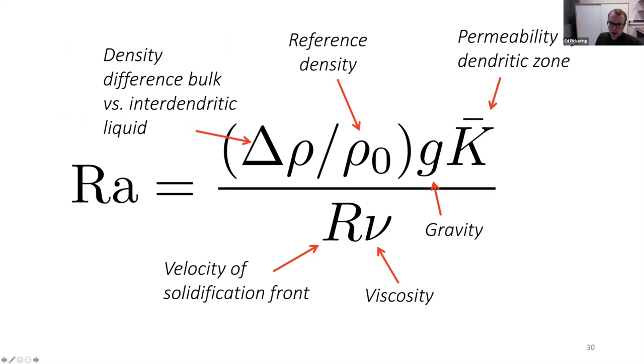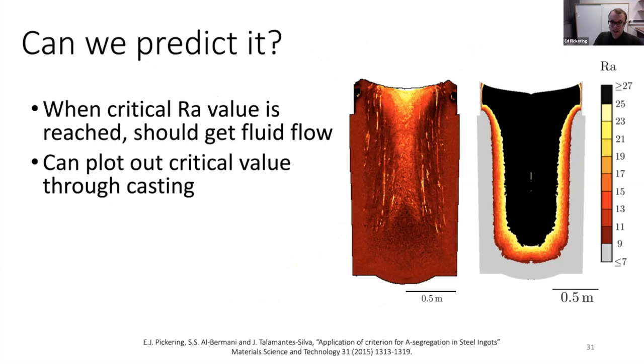And using the results of a thermal simulation, you can essentially plot that value out through a casting, which is what I've done on the right-hand side, and compare it against where your A-segregates actually start to form. And in this case, you see that when the Rayleigh number reaches greater than or equal to 7, it seems to be the cutoff between where we have non-segregated solid to begin with, and where we have this segregation starting to take place.